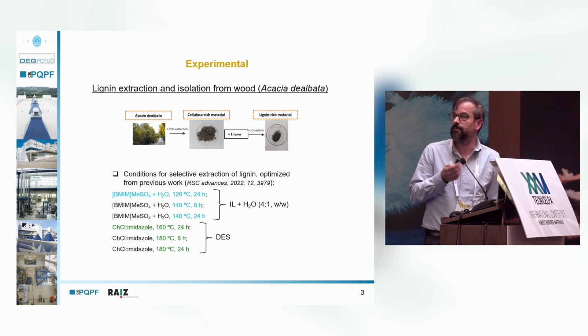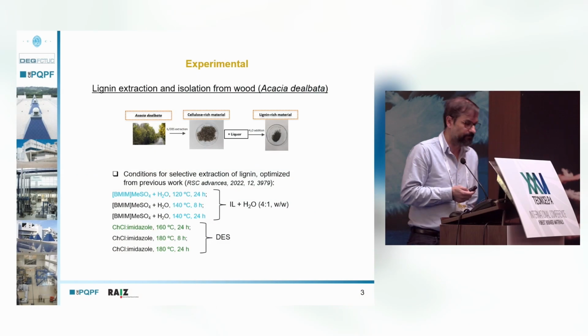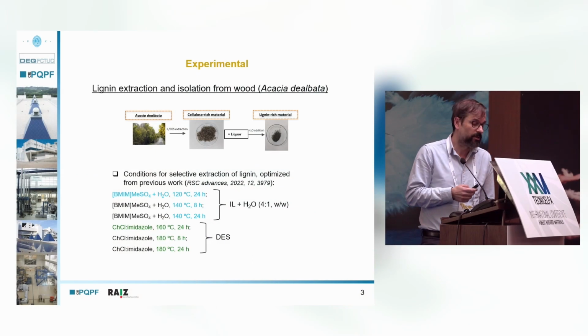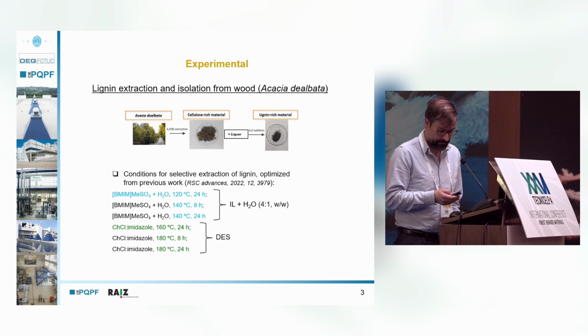So it was used an ionic liquid, which was butyl-methylimidazolium methyl sulfate, mixed with water in the proportion of 4:1, and it was used as a eutectic solvent, choline chloride imidazole solvent. The extraction with deep eutectic solvent required higher temperature, but afforded a more selective extraction of lignin. The conditions for extraction of lignin were optimized from a previously published work.